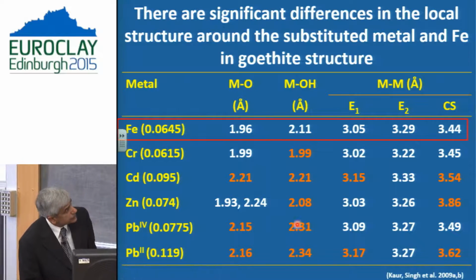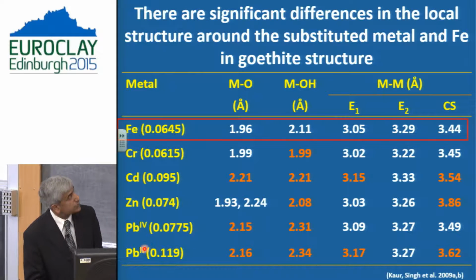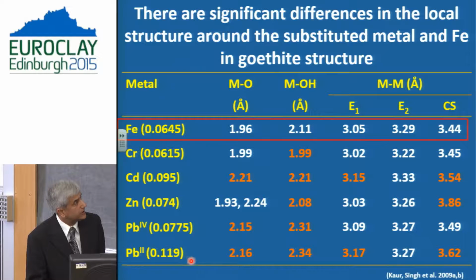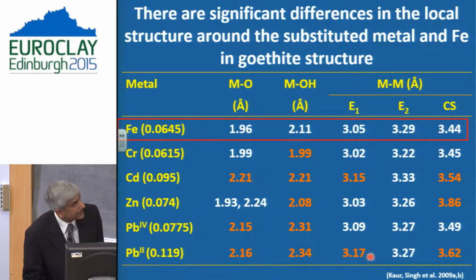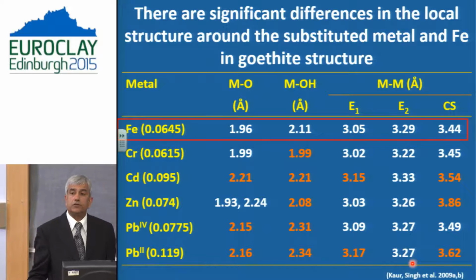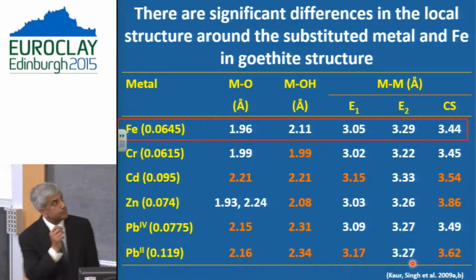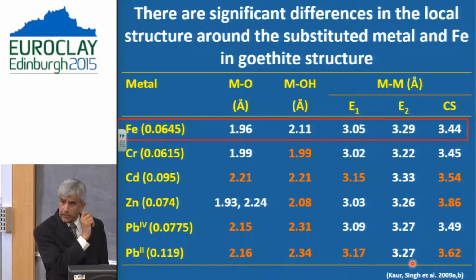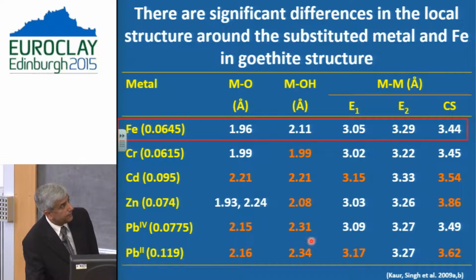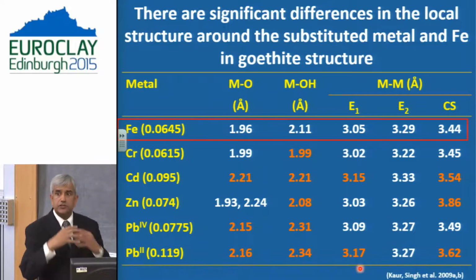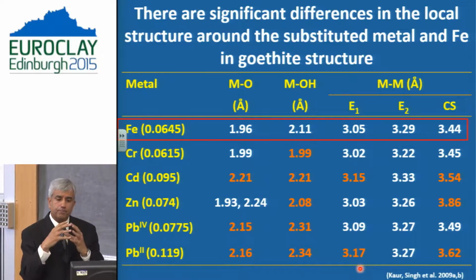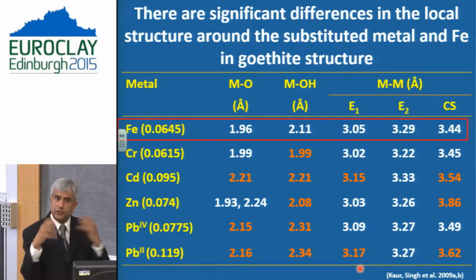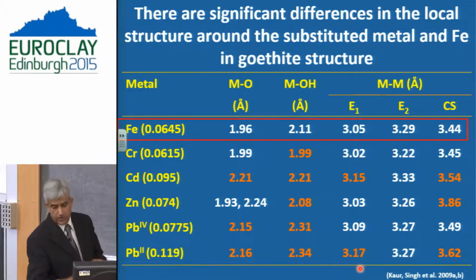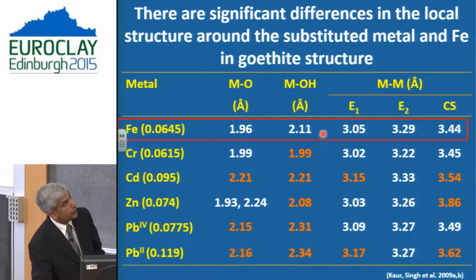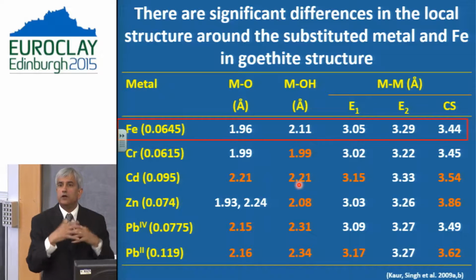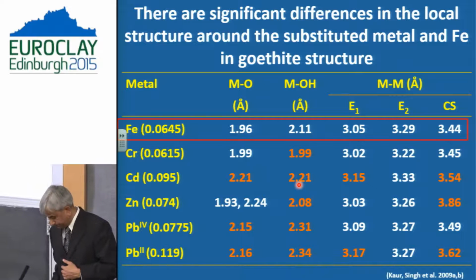For lead, the situation was quite different. We were able to put only a small amount of lead in the structure, and you can see that there are some rather large changes in the local structure in the goethite. And that's why, because of these big changes in the structure, the crystals were not bigger, and the structure was not able to accommodate a large amount of these elements. Where the strains are smaller in the structure, those elements can fit in large proportion or large amounts.